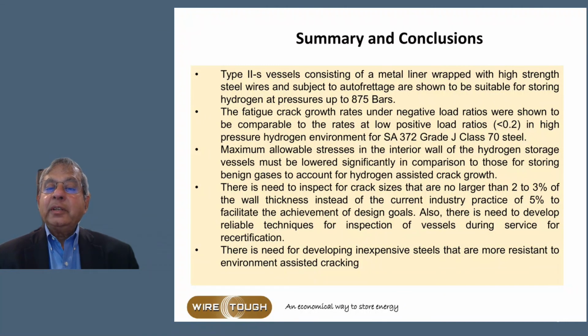Maximum allowable stresses in the interior wall of the hydrogen storage vessels must be lowered significantly in comparison to those for storing benign gases to account for hydrogen-assisted crack growth. There is need to inspect for crack sizes that are no larger than 2 to 3% of the wall thickness instead of the current industry practice of 5% to facilitate the achievement of design goals. Also, there is need to develop reliable techniques for inspection of vessels during service for recertification. There is need for developing inexpensive steels that are more resistant to environment-assisted cracking.